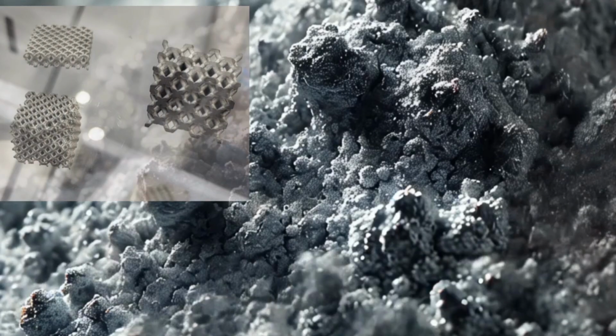In contrast, LPBF fabricated magnesium aluminum alloys exhibit corrosion resistance comparable to cast alloys. Some compositions show stabilization of degradation rates over time, aligning closely with cast counterparts. In addition, enhancing antibacterial properties through the addition of copper has been explored, but copper inclusion accelerates degradation, highlighting the trade-off between antibacterial effects and corrosion resistance.